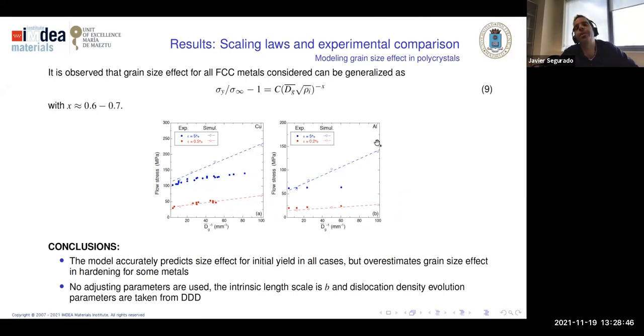Depending on the lattice and on the material, copper or aluminum, the model works better or worse with respect to this equation and to experimental values. In aluminum, it works perfectly. In copper, it works differently, and this is due to the storage of dislocations, which is not explicitly treated here. But the model is able to predict many cases for the same metal and when fitting with other metals. What is the effect of grain size? What is important here is that we are not using a very simple phenomenological law. We are putting in the real microstructure. So we are considering the actual texture, and we are putting in the actual grain misorientation and grain size distribution, not only the average.